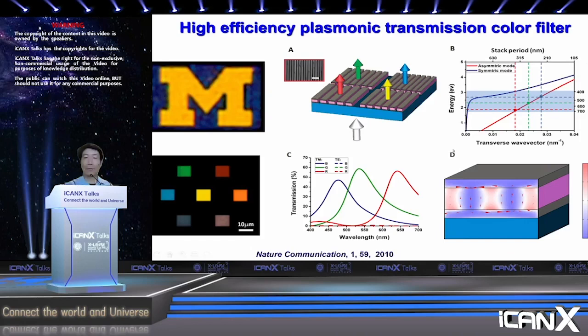And these structures, again, are pretty tiny, right? The period ranges from a couple hundred to 300 nanometers, depending on the wavelength. The total thickness is actually very small. These are one or two orders of magnitude smaller than what you would do with typical colored pigments. So at that time, this generated some interest because it transmits polarized light, simply just by patterning. Now, it's very compatible with LCD, liquid crystal display.